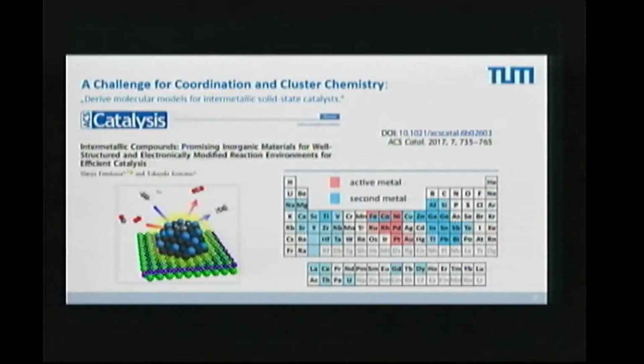So now boiling it down to the simplistic inorganic synthetic chemist, oh, fantastic. That's a playground. And my playground is the blue ones and the red ones. So I like to combine the aluminum and the gallium. Okay, I admit gallium is not an abundant metal, but it's close to aluminum, which is abundant. And if aluminum is too difficult for us, then we train with gallium. And we have the zinc, and we have these abundant metals, iron, cobalt, nickel, and so on. And alloys of them, intermetallic phases of them, they may be interesting for catalysis. So this is the far goal. We are not yet there. Many other people try it.